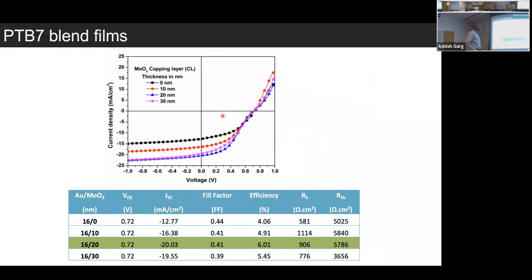What we did then was, instead of P3HT:PCBM, we used a higher efficiency material, which is PTB7, and the PTB7 devices on glass give you an efficiency of the order of 7 to 8%. And remarkably, when we make these devices with the top electrode consisting of this dielectric-metal-dielectric stack, this gives an efficiency of 6%. So 6 divided by 8 is a good number, getting close to 80%, maybe between 70 to 80%.